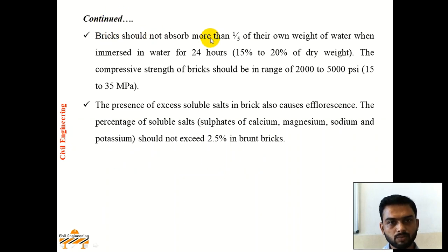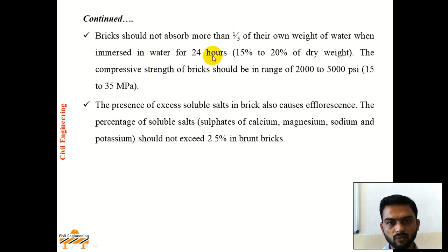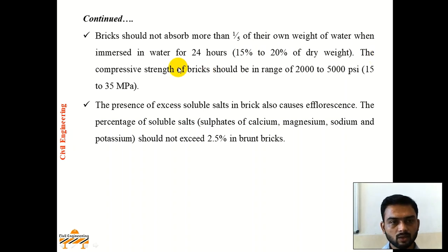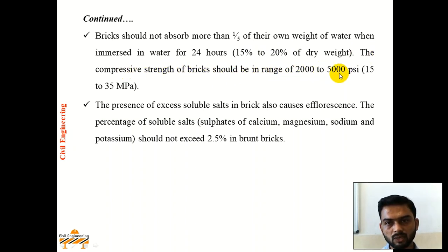Bricks should not absorb more than one-fifth of their own weight of water when immersed in water for 24 hours, i.e. 15–20% of their dry weight. The compressive strength of bricks should be in the range of 2000–5000 psi, i.e. 15–35 MPa.